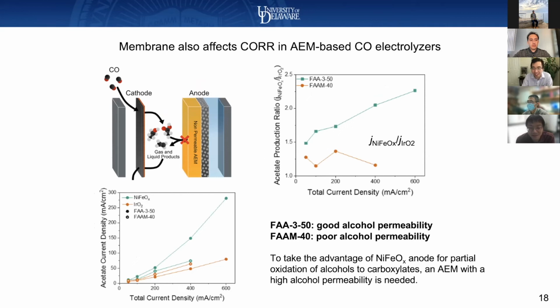This is an excellent question. There's a thought we're actually trying to do, which is to pick a catalyst that can fully oxidize alcohol to CO2. There's a bunch of catalysts that can be considered, but the challenge there is the end product is CO2. It's hard to quantify how much alcohol got produced internally and went through this process, eventually ending with CO2 again. This is one of the technical challenges that kind of stops us from exploring those catalysts. But if you can quantify a small amount of CO2 coming out of this anode chamber, I think in principle you can study that. Yes.